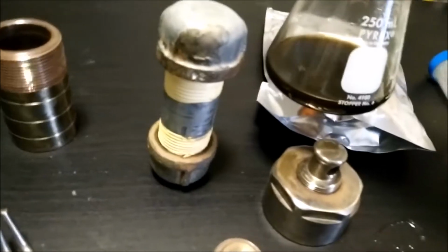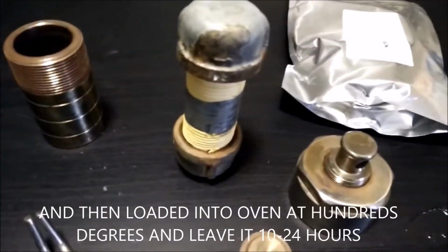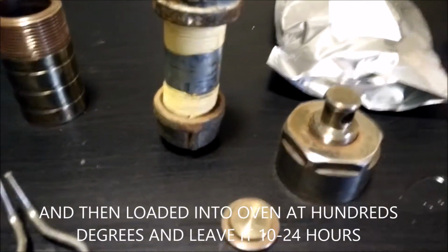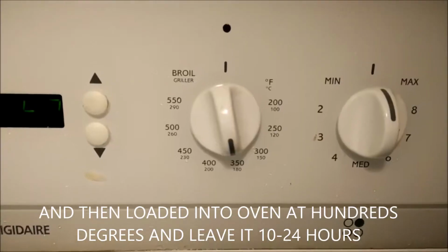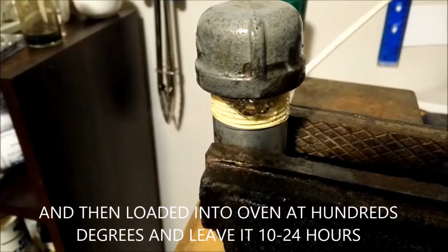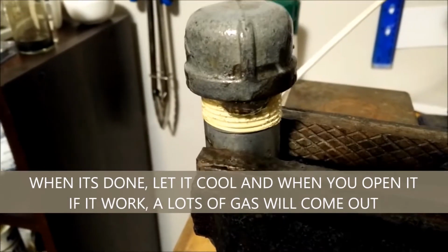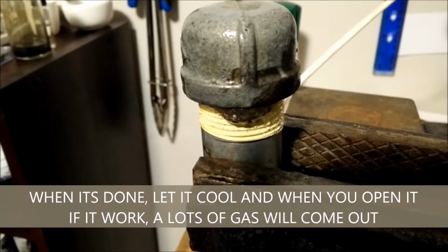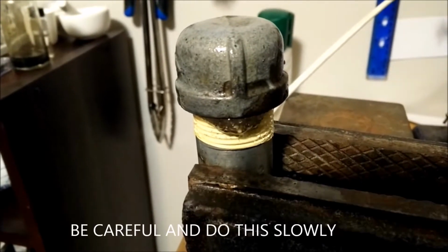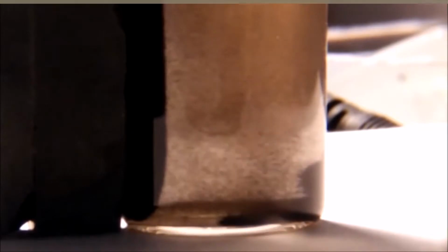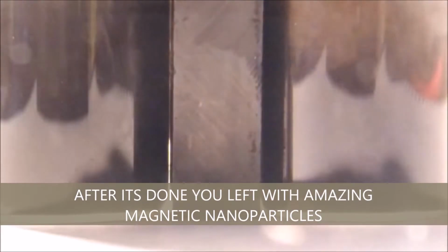I showed and explained both of these in a previous video. And then load it into an oven at 180 degrees and leave it for 10 to 24 hours. When it's done, let it cool, and when you go to open it, if it worked, lots of gas will come out, but be careful and do this slowly. When it's all done, you're left with amazing magnetic nanoparticles.